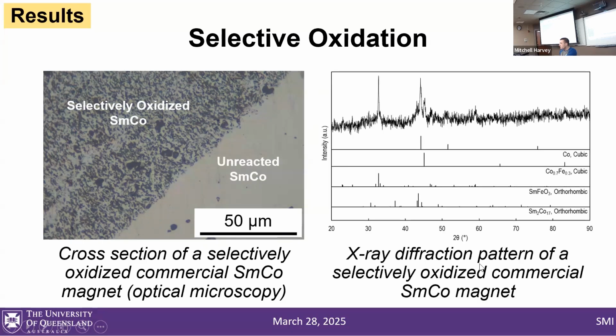If we do X-ray diffraction on this—X-ray diffraction helps us determine what crystal phases are present—we can see that we have cobalt metal, probably some iron and cobalt metal in solid solution, samarium ferrite, and the unreacted intermetallic. This is a pretty noisy scan; it's hard to get a good scan on this with the copper tube, but we can see pretty confidently that we have both cobalt and samarium ferrite. So the overall reaction we were showing before, we're pretty confident it's progressing as we predicted based on thermodynamics, and this is also backed up with some other literature results.